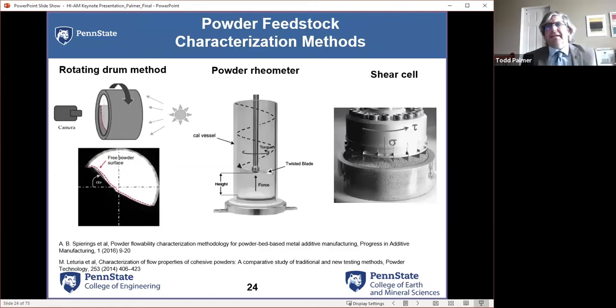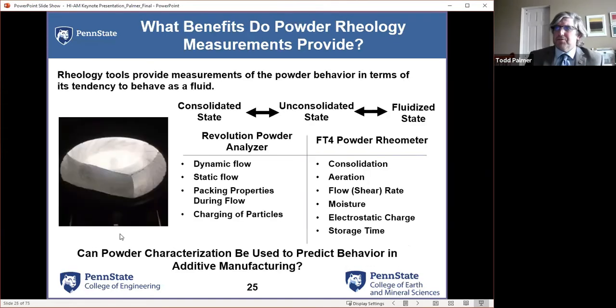Now, this led us into trying to take a look at rheology tools, because we're seeing differences in sphericity. We're sort of saying, okay, do these powders really vary? And when it comes to rheology, there are three that I want to focus on. One is a rotating drum method, where for the most part, you take a drum of powder, take a known volume, and rotate it around.